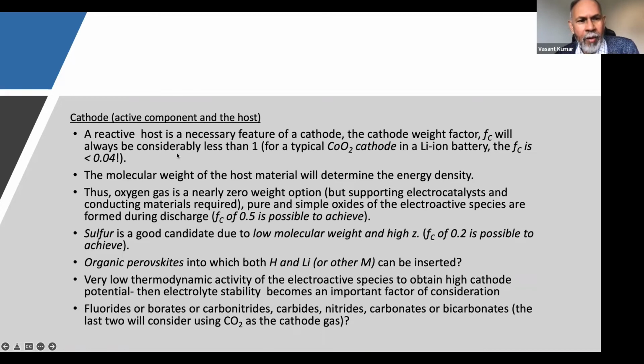For a cathode, we can't avoid a reactive host because essentially it is a material which stabilizes the electroactive material to a very stable phase. The more stable it is, the higher is the potential available from that cell. And the cathode weight factor, FC, will always be considerably less than 1. We do not want it to be too low, but take a typical cobalt oxide cathode in the lithium-ion battery used in a mobile phone or a laptop. This factor is 0.04. So for lithium the capacity is massive, but cobalt oxide molecular weight is quite high. So that determines energy density for that cathode.